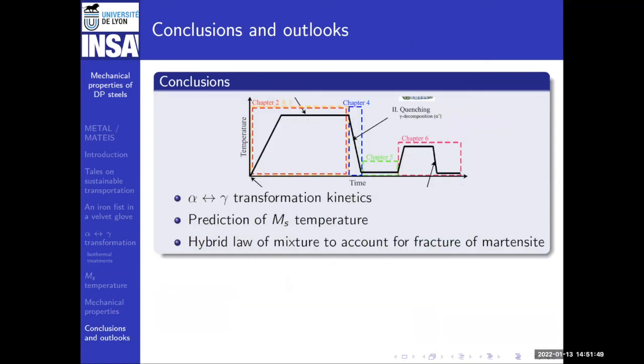So it's time to conclude, and I promised to leave you at 3 o'clock. If I conclude, I talked about a ferrite to austenite transformation kinetics model that was used as an input parameter to predict the MS temperature, the temperature at which martensite starts, and from the knowledge of the percentage of each phase, we could build a hybrid law of mixture that accounts for the fracture of martensite that was observed above 4% of deformation.